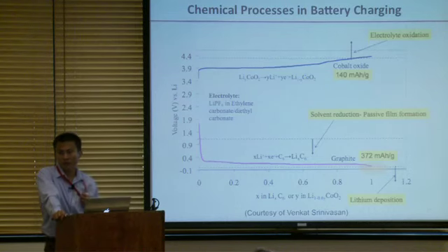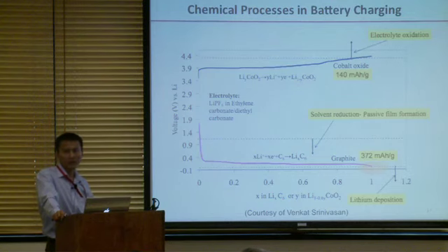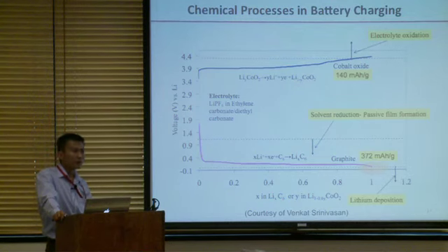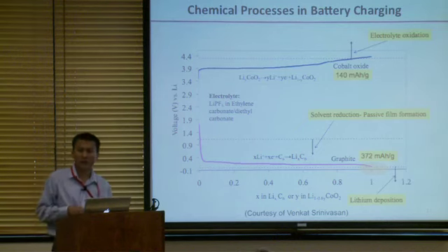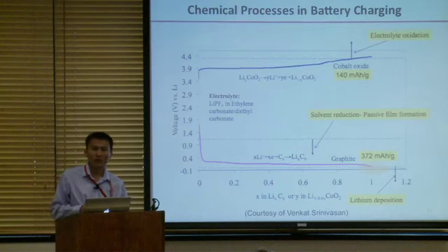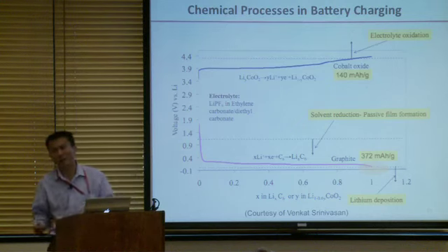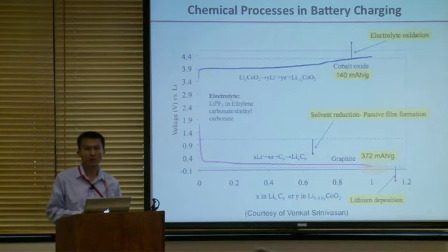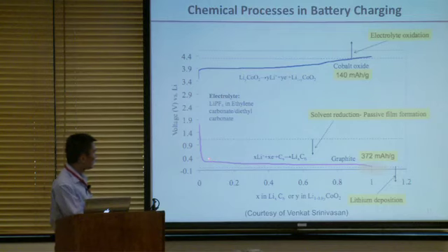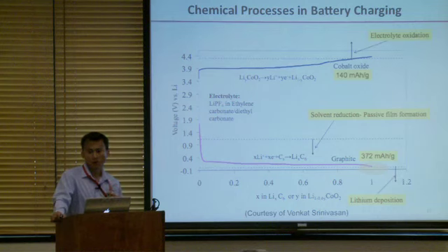Now come to the fast charging. How do you do fast charging? You drive a lot of current through it, and you have overpotential. You have a kinetic process that cannot react so fast. And then what the charger does is you just put in higher and higher voltage, right, to drive the current you like. At the end, when you put in more voltage, this carbon electrode can go below the lithium metal deposition, electroplating potential. You're going to plate out lithium, and then the battery explodes.